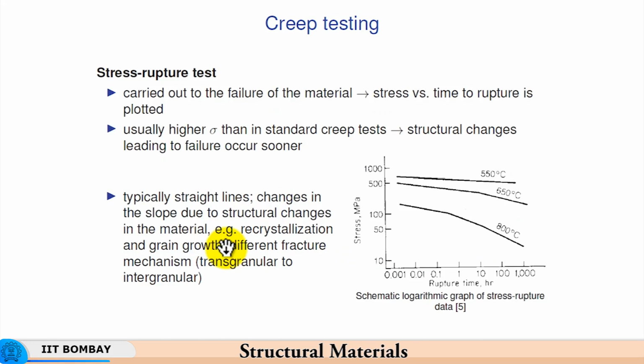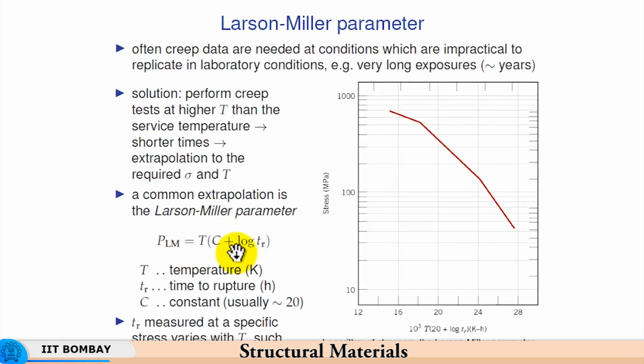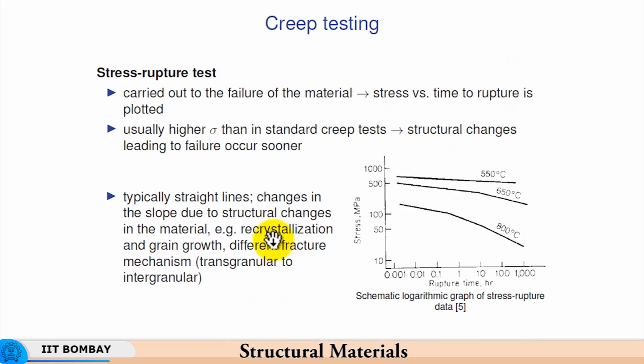So, what we need to do is combine the effect of temperature and time. If the temperature is higher, time for rupture is lower. If temperature is lower, time for rupture is higher. As we see here from this creep rupture test also, for a given stress, for high temperature you have a smaller rupture time. For 550 you have larger rupture time, and for 800 degrees centigrade it will rupture faster. So, the stress is lower and rupture is faster.